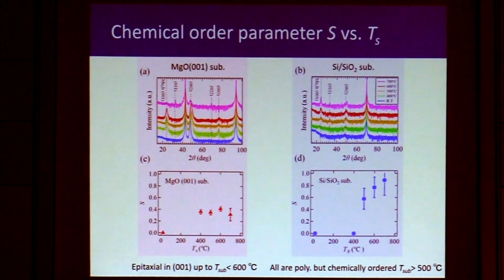What is the thickness of your film? 20 nanometers. So that means you haven't measured the out-of-plane lattice constant yet, right? No. If you compare the in-plane lattice constant a with the out-of-plane lattice constant c, you will find they are unequal. That gives you a tetragonal distortion which can break the cubic symmetry. That's why you see this effect. Otherwise, the switching field would be huge.